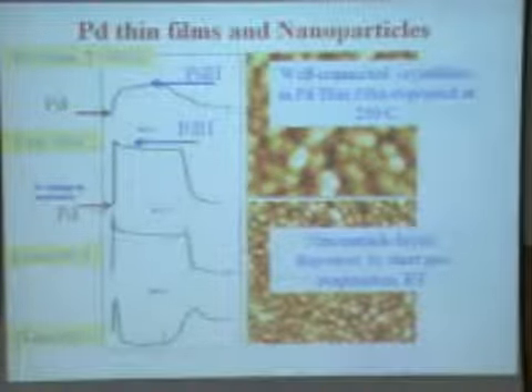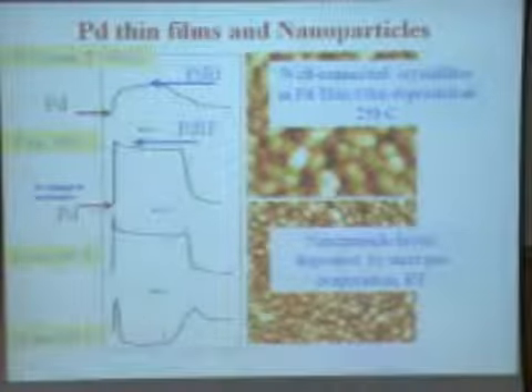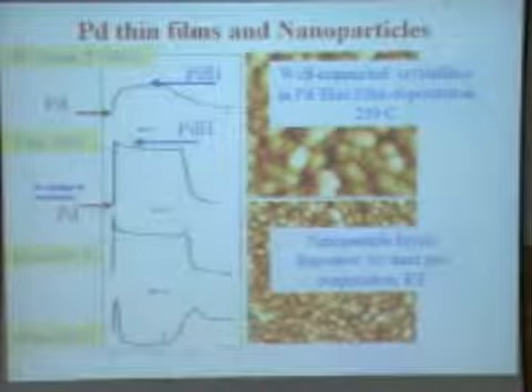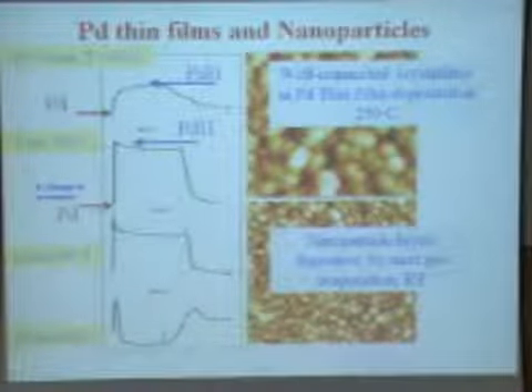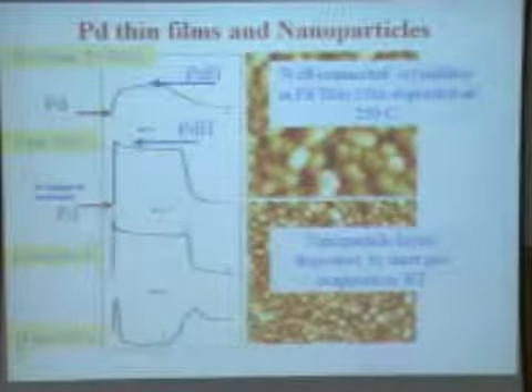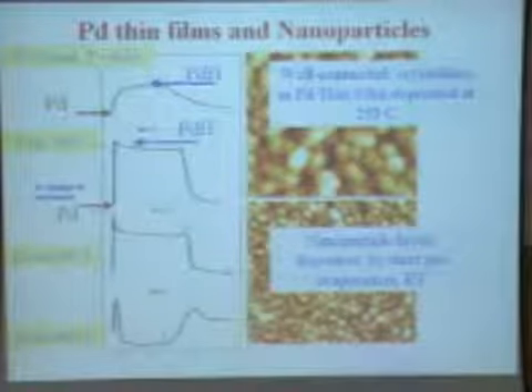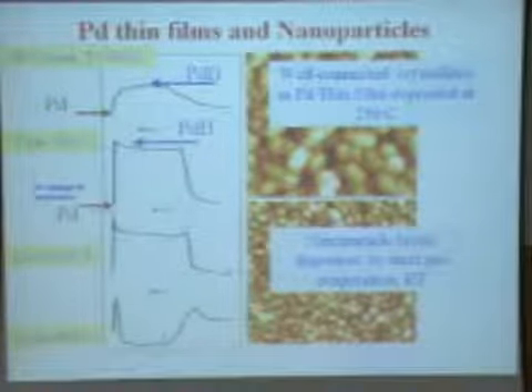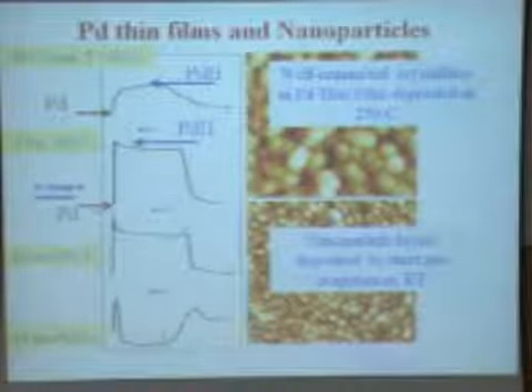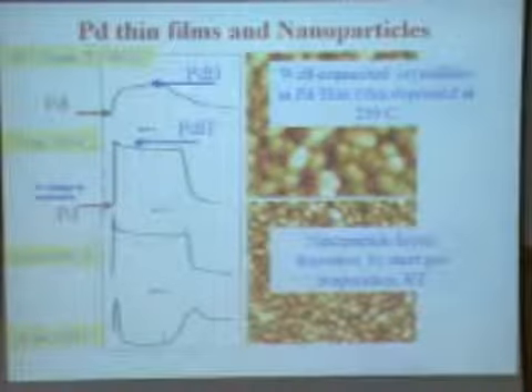You can see how a palladium thin film responds to hydrogen, and how a palladium nanocrystalline layer responds to hydrogen, is totally different. And the only thing we have done is, in place of the vacuum, we have introduced an inert gas. These large crystallites were deposited at 250 degrees centigrade, and we expect them to be connected to each other because they are grown at high temperature. These small crystallites are grown at room temperature, so they have some loose topography. Later on, we will explain why it's happening.